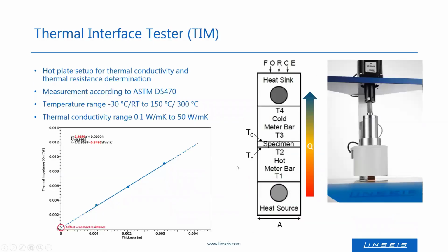The TIM tester works differently, so it's a steady state measurement method with two plates which heat up and cool the sample so that a stable temperature gradient over the sample is achieved. So one has a hot and a cold meter bar, and the specimen is clamped in between, like it is also shown here. And one waits until the temperature distribution is stable. One measures here the thermal impedance of a material, and one measures 3 different thicknesses, so that one achieves a curve like that. And based on this information, one can then determine the thermal conductivity.